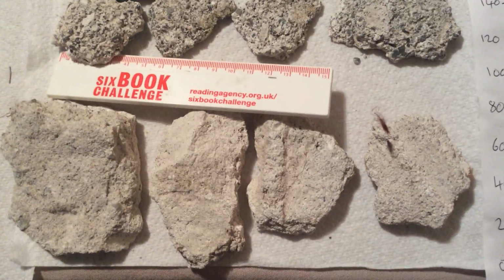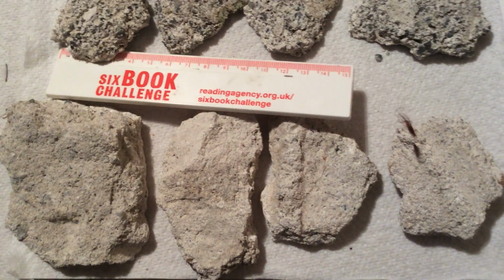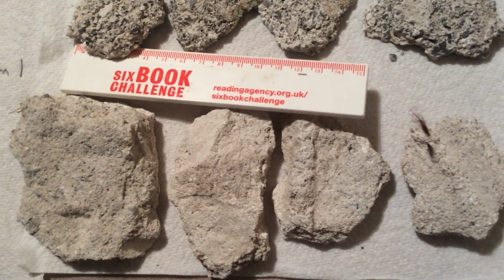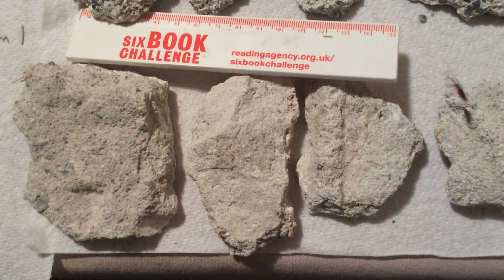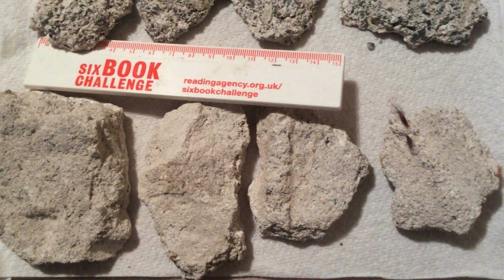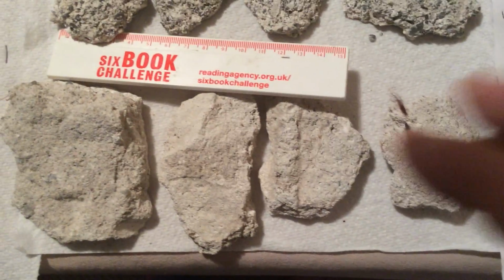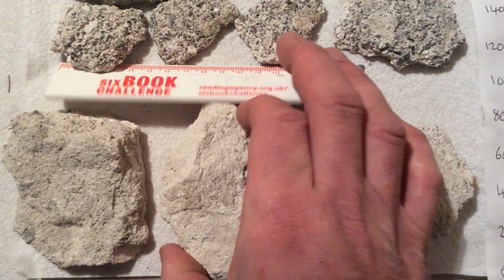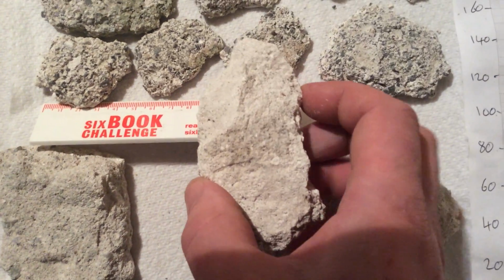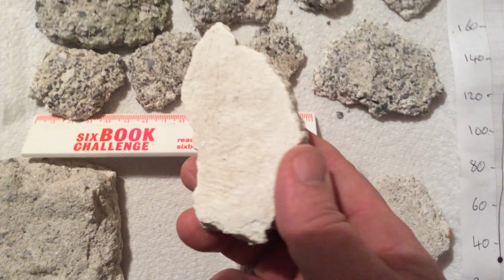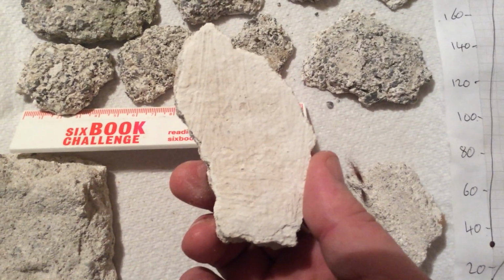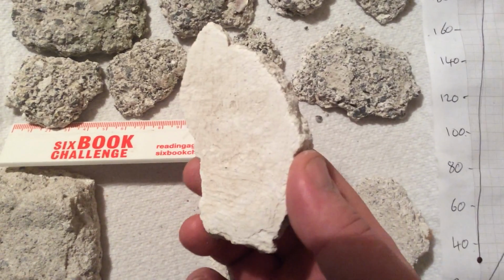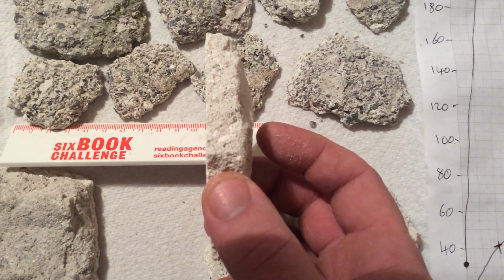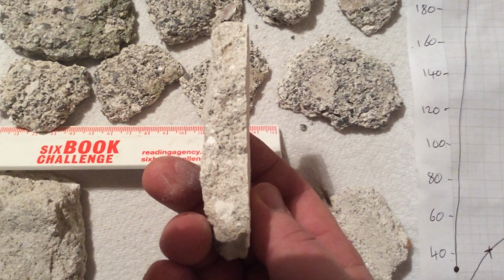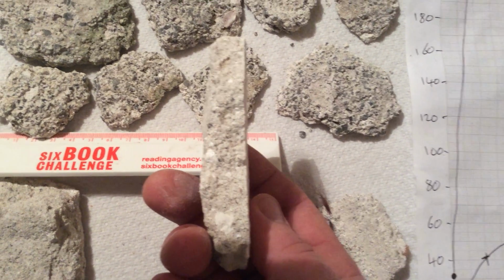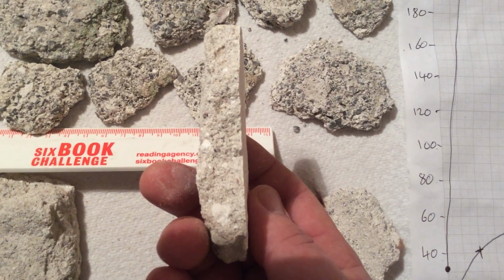On the inside material, see the scale of the porosity is much finer, and you don't see many large aggregate particles. It's a denser material, it's more mechanically robust. That's the back side, and you look at the front, which contains a beautiful lime wash, and you can just see the lime wash has penetrated a few millimeters into the surface.